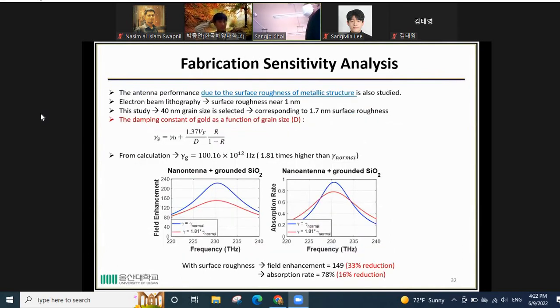We also analyze the fabrication sensitivity because of the surface roughness during the fabrication. So nowadays the electron beam lithography has a surface roughness near 1 nanometer. So in this study we use 40 nanometer grain size, which corresponds to the 1.7 nanometer surface roughness, and also we calculate the damping constant as a function of the grain size. So from calculation, with considering the surface roughness, the damping constant becomes 1.8 times higher than the damping constant of the normal conductor.